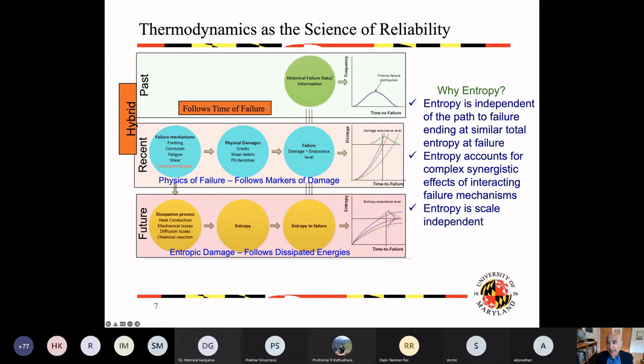So why do we use entropy? Entropy is independent of the path to failure. So we could always say that it very much depends on how much stress you put. But once the entropy reaches this level, regardless of how it reached it, whether through a quick path to this level or a very slow path, once it reaches this level, a failure occurs. Therefore, entropy is independent of the path to failure.